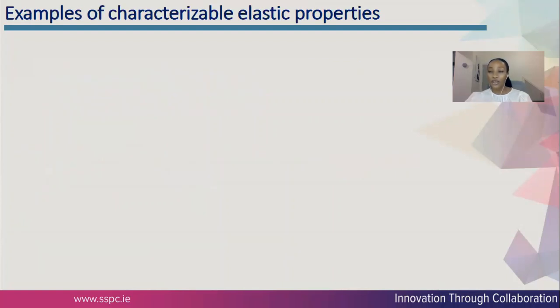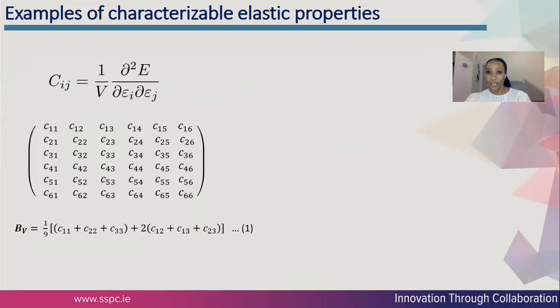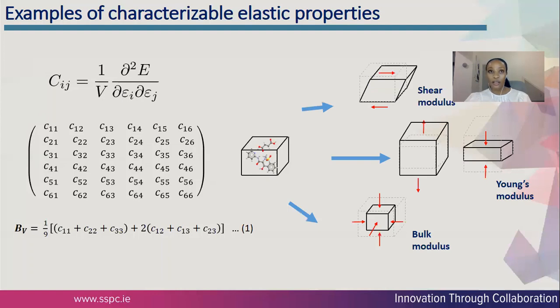But before we get into how each method performs, it is worthwhile to mention that the elastic properties are determined from elastic constants, which are themselves components of the stiffness matrix and second derivatives of energy with respect to strain. Essentially, when we compute elastic properties, we actually compute the stiffness matrix. And from the elastic constants, properties such as the shear modulus, the Young's modulus, and less relevant to this talk, the bulk modulus can be determined.